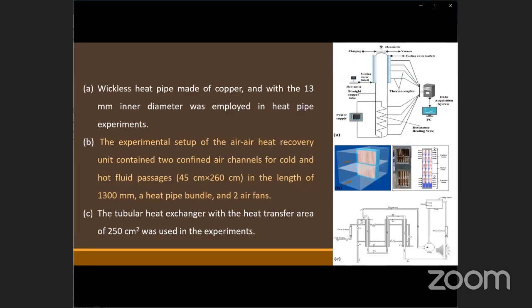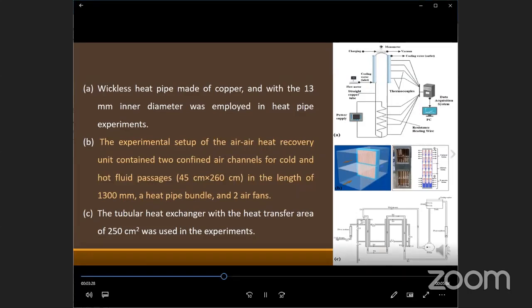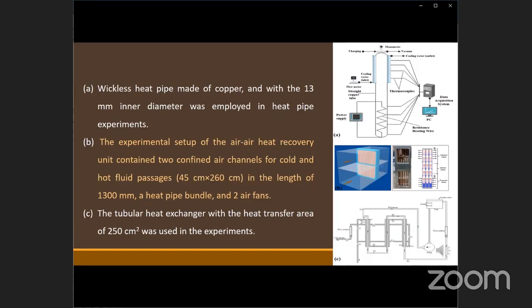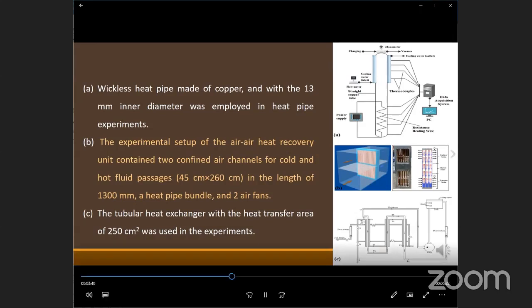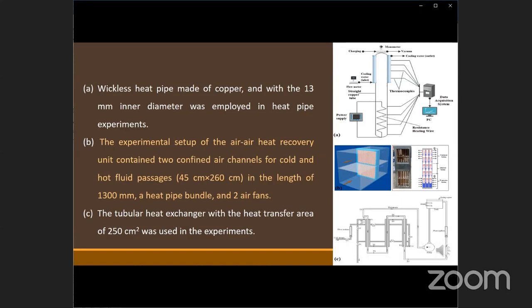Schematics of the test rigs used in the experiments can be seen in these figures. As you can see, the wickless heat pipe was made of copper and it has a 13 mm inner diameter. The experimental setup of the air-to-air heat recovery unit contains 2 confined air channels for cold and hot fluid passages, 1300 mm in length, a heat pipe bundle, and 2 air fans. The tubular heat exchanger, with a heat transfer area of 250 cm², was used